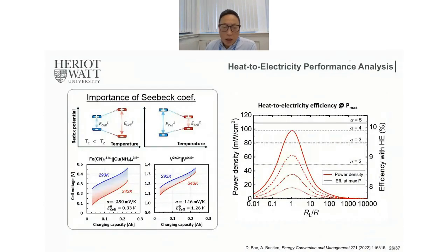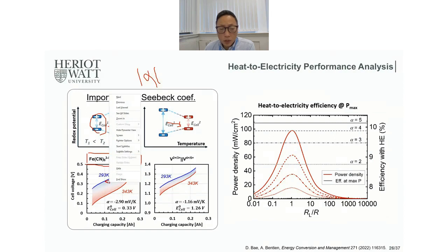Now let's talk about the Seebeck coefficients, in other words, the thermogalvanic coefficient. No matter how this cell voltage changes at different temperatures, it can be large or it can be small. The important thing is the overall absolute value of the thermogalvanic coefficient should be as large as possible to make this kind of system a very highly efficient system. So let's talk about the ferrocyanide with the copper triamine system. In these two combinations, the good thing is they have a very huge difference between the high temperature and the low temperature in terms of the cell voltage, in terms of charging capacity.